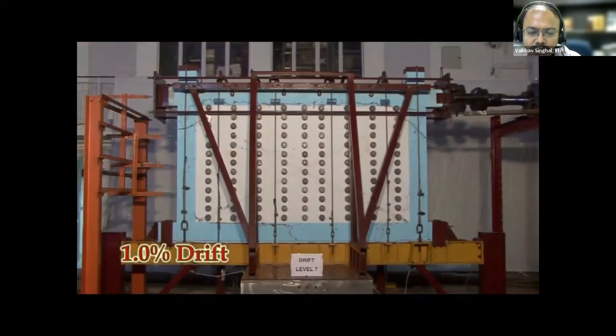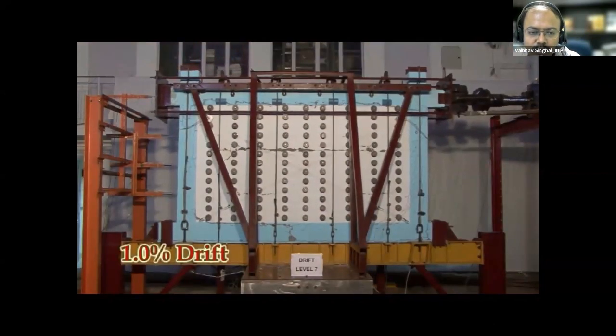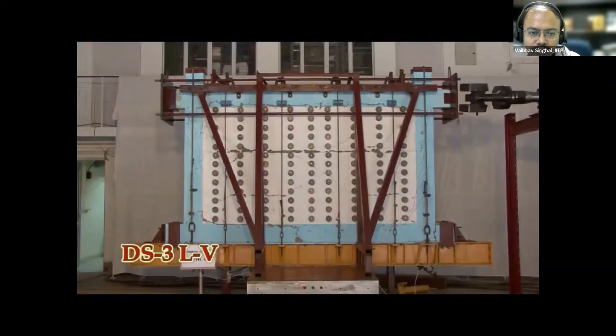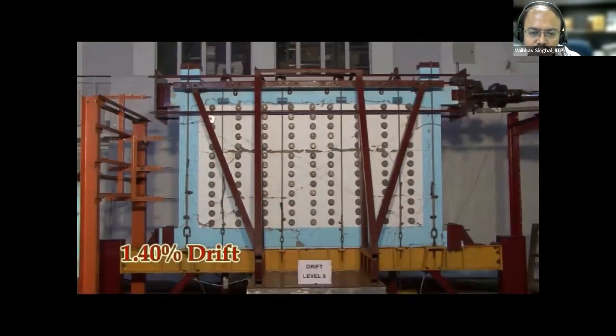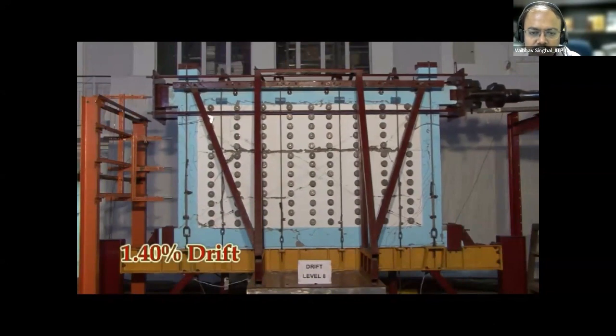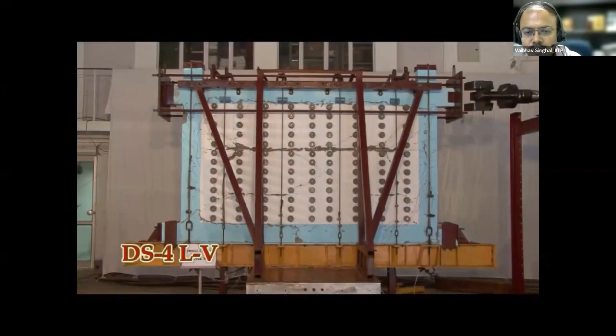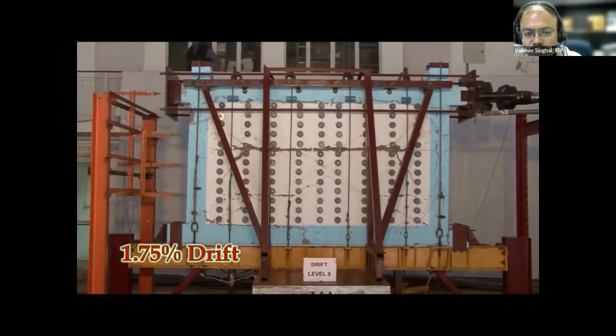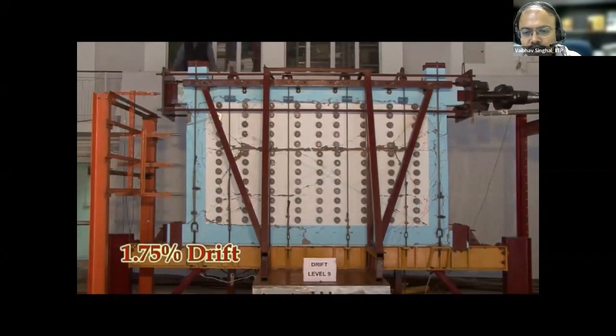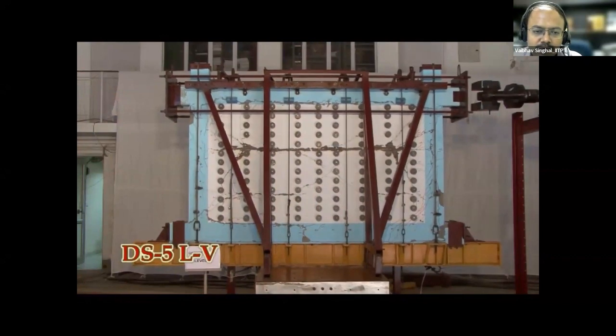So under the out of plane response, there was no damage, no excessive deformation. And you will see the first time there is a horizontal crack. So this is all happening because the masonry is also contributing. The masonry is also taking a good amount of forces, and it is also participating in taking the in-plane forces.